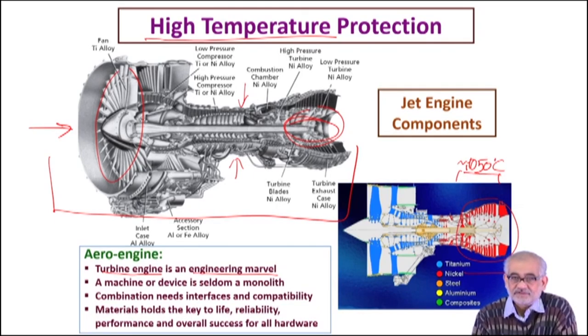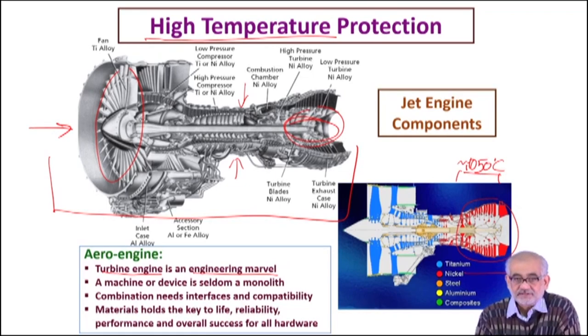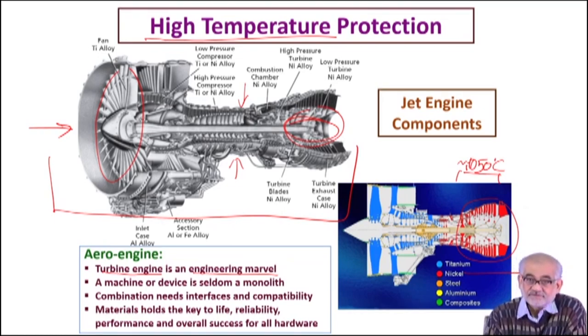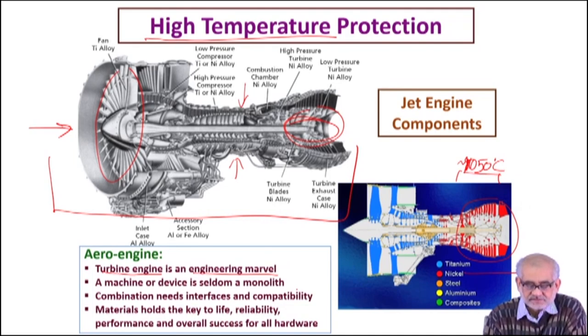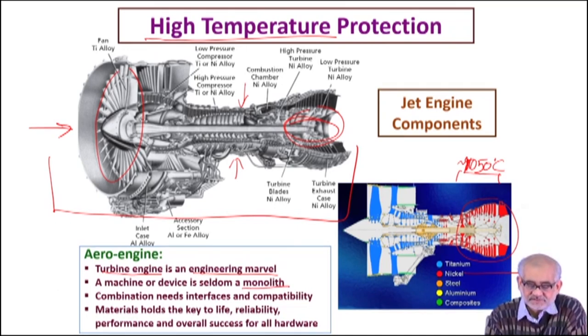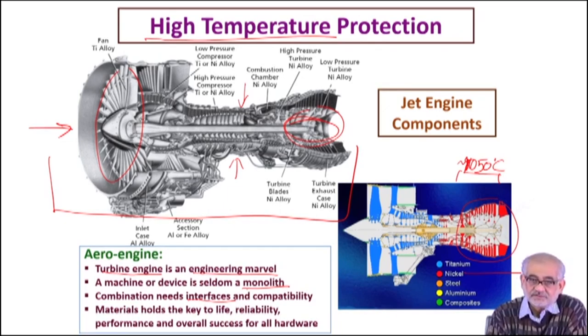To have all those 8 to 10 alloying elements into a single solution and retain them through a process of solidification which leads to not only a usual polycrystalline aggregate, but actually a single crystal, is enormously difficult. Yet these blades which make up the turbine part at the combustion zone are made from single crystal nickel-based superalloys. Protection of these alloys at high temperature and high oxidizing conditions is a major issue. All these major engineering components are multi-component systems and they have interfaces.